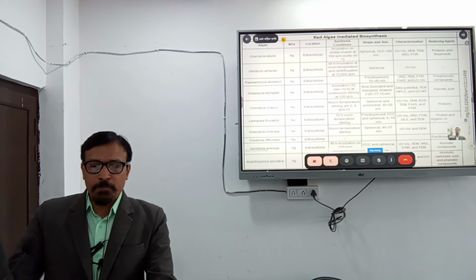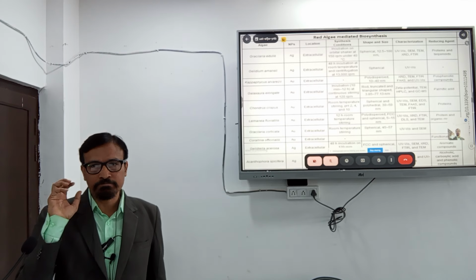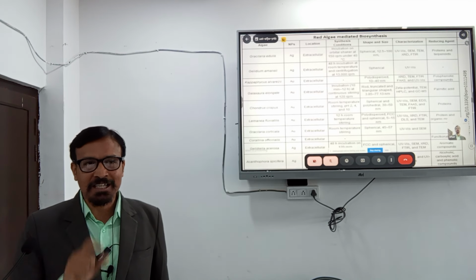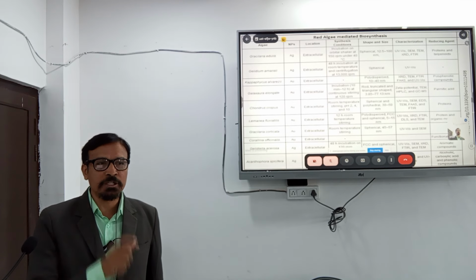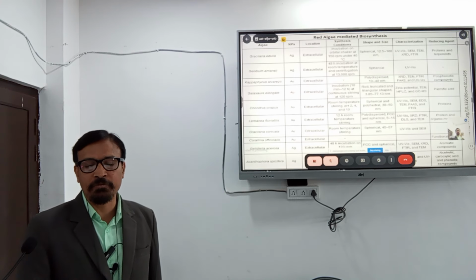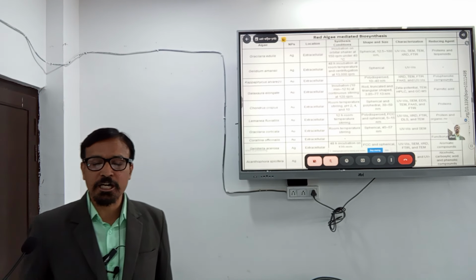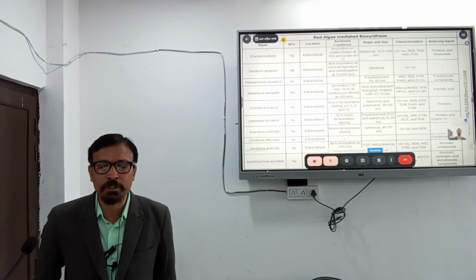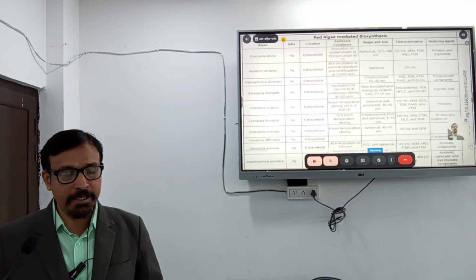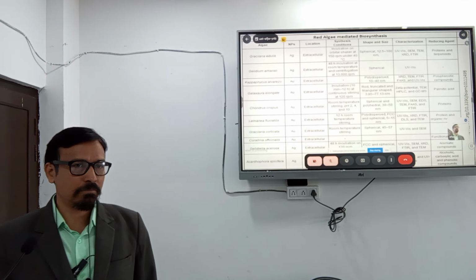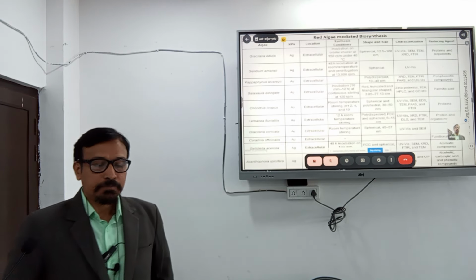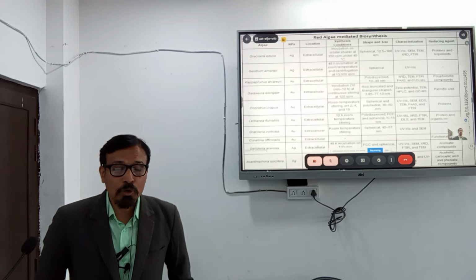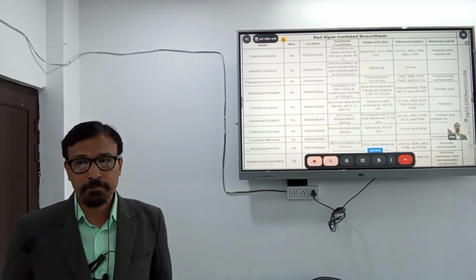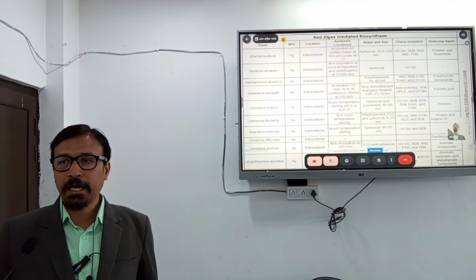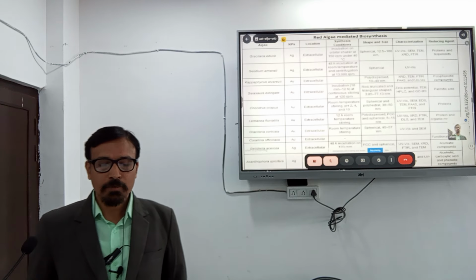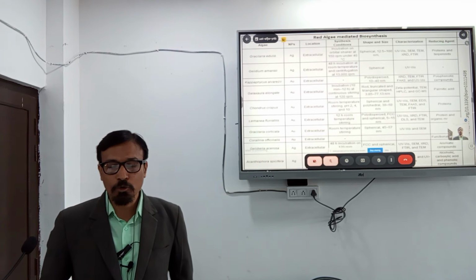And the polydispersed FCC face centered cubic structures and the spherical structures will be produced in the size range of 5 to 15 nanometer, and the characterization of those nanoparticles can be done with UV vis, XRD, FTIR and SEM. So next is the Corallina officinalis. Okay, this is another algae, with which we can produce the gold nanoparticles.